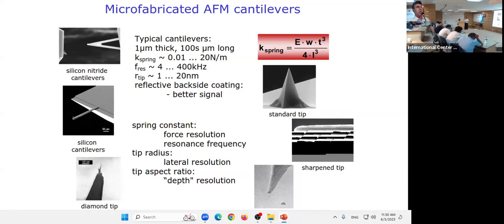But if you have locked the resonance frequency of that sample, keeping in view the natural resonance frequency of the tip, then it is fine. So it is important that you lock the resonance frequency each time. Otherwise, if there is any kind of dirt or impurity on your surface, or if you cough in front of the sample or the cantilever, something from your breathing will attach to the cantilever, because we are talking here about pico-Newton forces of interaction between the tip and the sample. So it is very sensitive. That is the reason that imaging, or just working with the system, needs in-depth understanding. Then it would give you reproducible and desirable results.